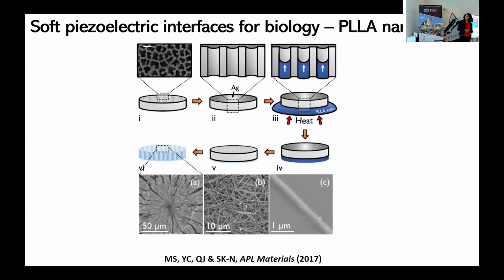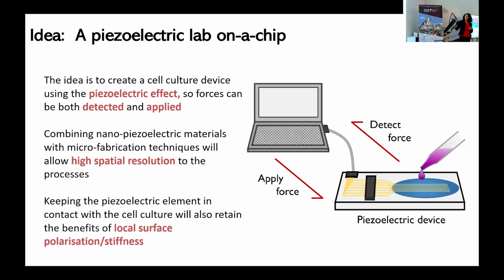So again, we do the similar treatment of growing these nanowires, again, because we want to get the alignment of the dipole, we want to control the crystallinity. The reason the piezoelectric effect is so interesting is because the idea was to create a cell culture device, actually, where we can use the piezoelectric effect to both apply a force and also to detect what is going on. Because remember, I can have an array of these nanowires. I can apply a field across them, and it'll cause them to bend or to stiffen up. And if there's anything that's happening at the top which is causing these nanowires to bend, I should be able to detect this as an electrical response. So sort of using this as an interface with cells.